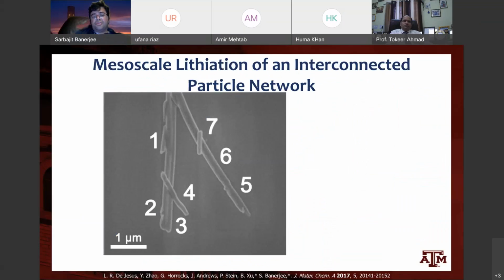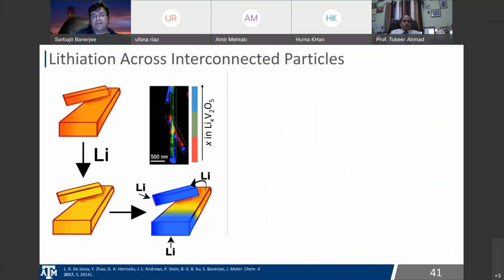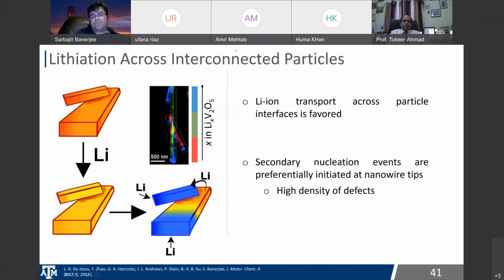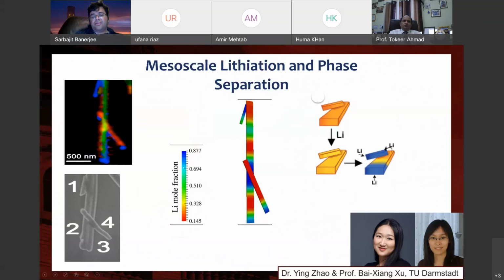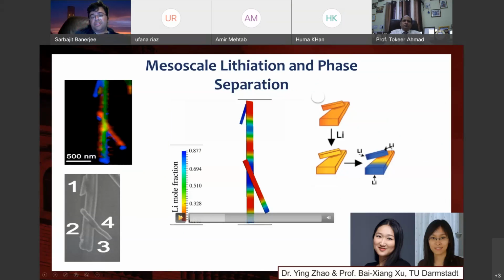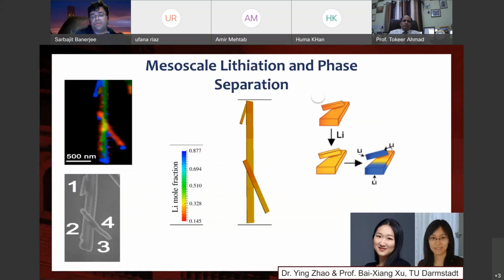And then we've also looked at these mesoscale heterogeneities across networks of particles. We see very large inhomogeneities. Typically, we see transport being favored across particle boundaries, and lots of secondary nucleation events happen at tips. And here's an example of a little movie. I'm glad I'm able to play it. You can see that lithiation is induced at tips, and then the lithium actually transfers between these two wires, so one particle ends up getting lithiated before the other one, right? So you have this particle-by-particle lithiation that takes place. This is work with Ying Zhao in Bai-Xiang Xu's group again at TU Darmstadt.